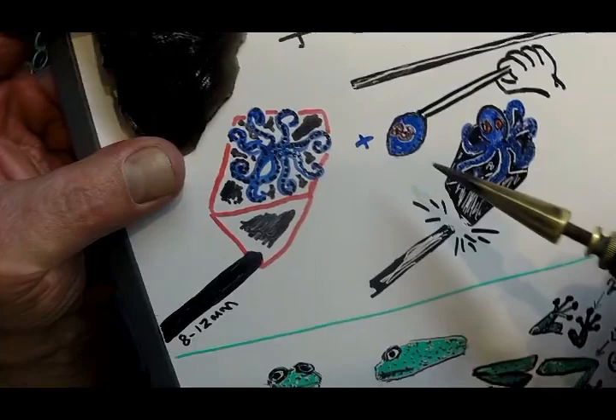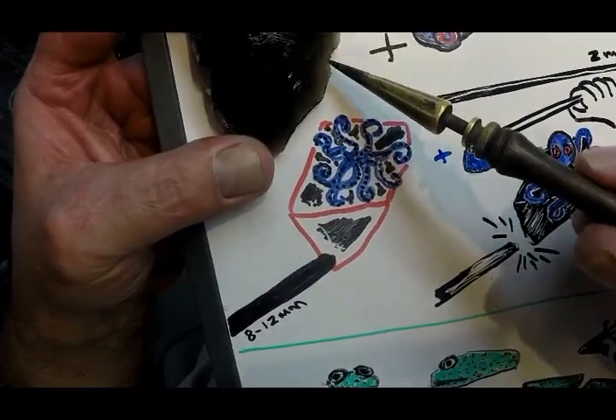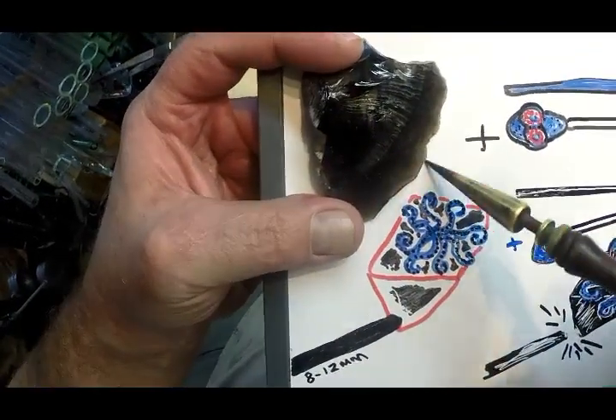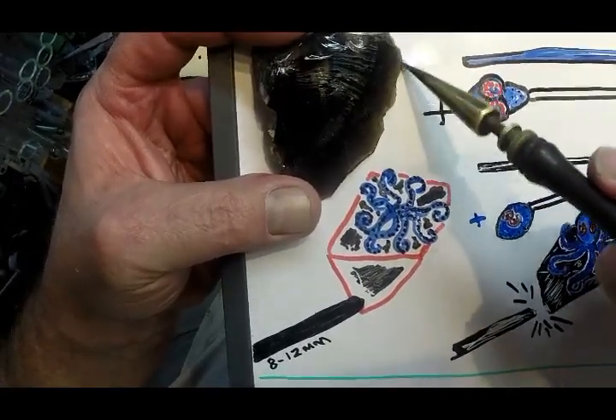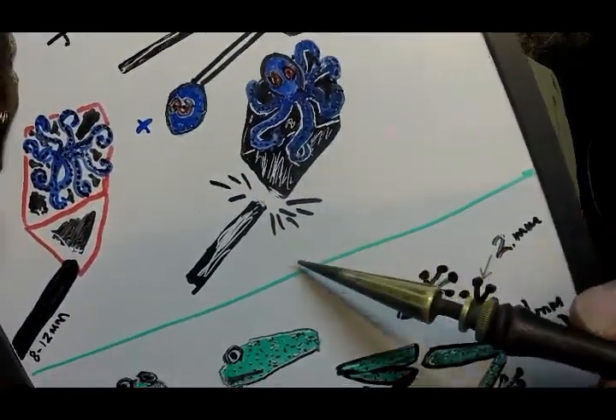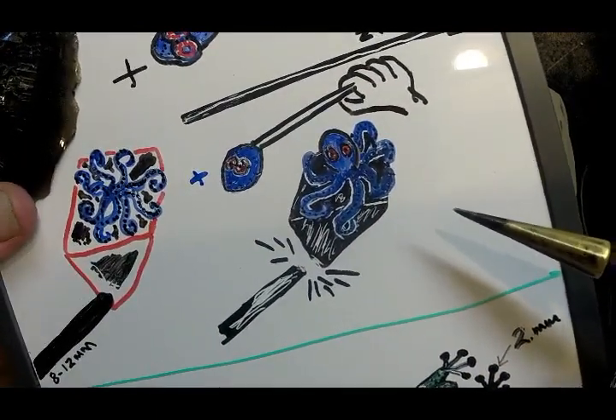We've got our head all ready and prepared, heated and on the obsidian, which is going to be glowing on the corners but not so much in the centers. Really try to avoid overheating those sharp edges as they will bubble and kind of turn white. So keep your piece away from those sharp edges. You can go over ninety-degree edges that have quite a bit of thickness — it disperses the heat well without devitrifying the edge of the obsidian. Just a little note. Once we've got it all drawn on there, we'll snap off the punty, put the piece in the kiln, bring it down real slow, and hope it survives — knowing we're dealing with some really low quality control material, but it's mass produced, so what do you expect from obsidian?